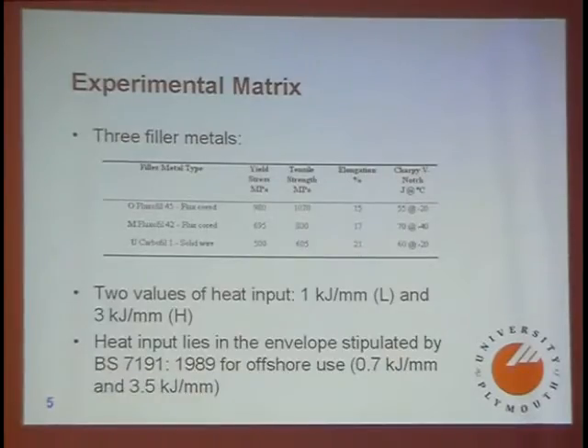And we used 3 filler metals, nominally corresponding to overmatched, matched, and undermatched in the tensile properties of the actual filler metal themselves. You can see that the overmatched has a 980 yield stress as against the sort of 800 of the roller quenched and tempered steel. This is close at 700 and that is low at 500.